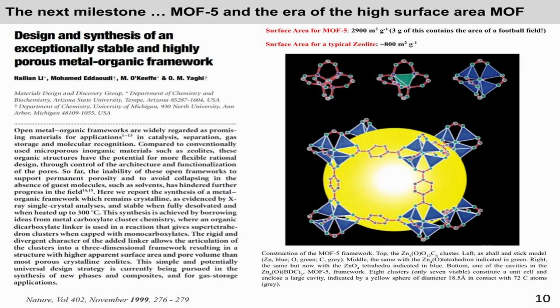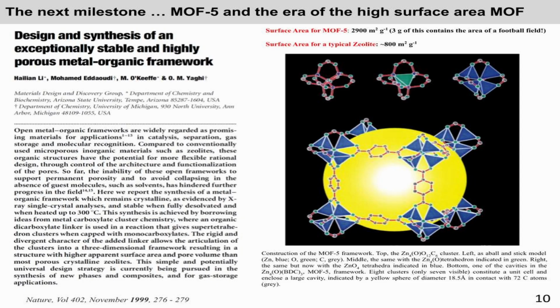It had almost a surface area of 2,900 meters squared per gram. Okay, to give you a scenario, 3 grams of this will contain the space that you have in a football field. So this was where you had a zinc node and you had these oxide linkages. You had the zinc oxide cluster, and the zinc oxide cluster would bind to this benzene dicarboxylic acid. You'll have two COOH groups on either side at the 1,4 positions, and they will form a strong bond between the zinc and the carboxylate group. So then these clusters together will form an extended solid, and it was very easy to make these MOFs.